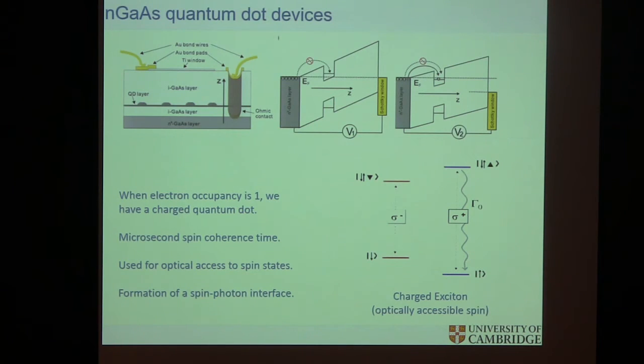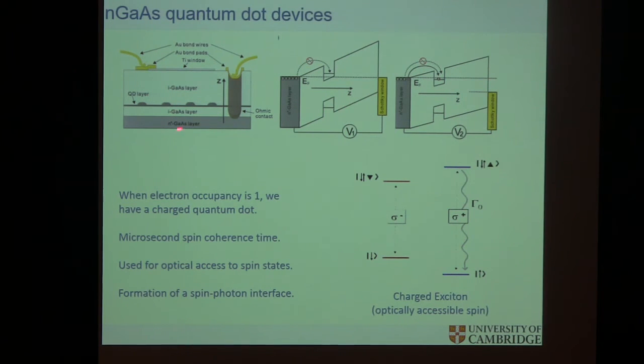So how do we work with these devices? We don't work with them bare. We actually put them in contacts. So these are these layers that sit there. And then we have an n-doped layer underneath, so it's an electron reservoir. And then we have a thin Schottky window above. And the whole thing is around 150 nanometers or so, it's very narrow.